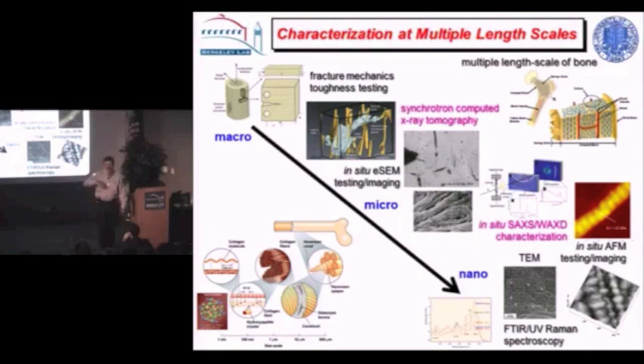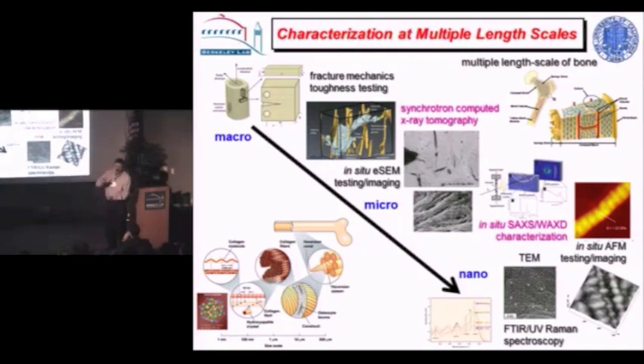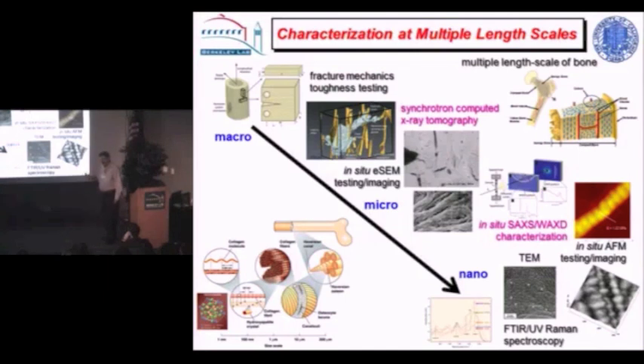With bone we use tomography to map out crack paths. We also do a lot of in-situ SEM, which is only two-dimensional but lets us see exactly how cracks interact with the structure. When we get down to hundreds and tens of nanometers, we use SAXS and wide-angle X-ray diffraction techniques at the ALS where we can look at in-situ deformation and see where plasticity comes from. We also use AFM and look at cross-linking issues associated with collagen in bone.